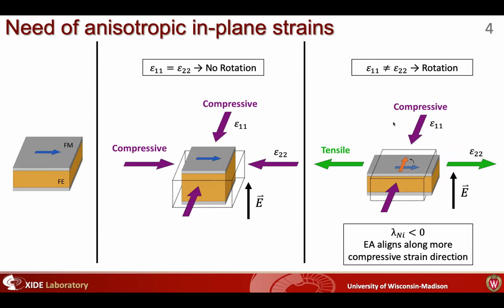For this to work, you need your piezoelectric material to exhibit anisotropic in-plane strains. If the strain is isotropic in-plane, there's no driving force to rotate this in-plane magnetism. So you really need these anisotropic strains. And for nickel, which is the only metal that we really worked with, it has a negative magnetostriction. So as I've shown in this schematic, it will want to align its anisotropy along the more compressive in-plane direction.